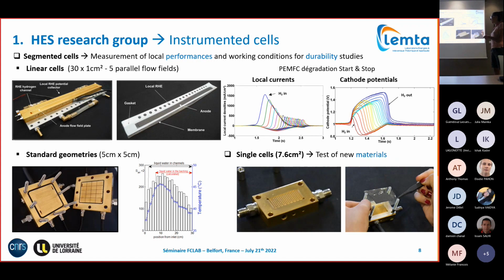Mostly we have a segmented cathodic flow-feed plate, where the current collector plate is segmented into individual, electrically isolated current collectors. In our last generation of cells, we have local reference hydrogen electrodes, which allow us to measure as well the local current profile and local electrode potentials, as shown here on the cathode side and at the other side.